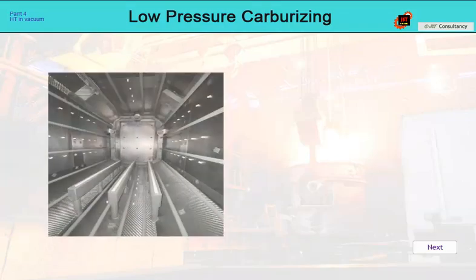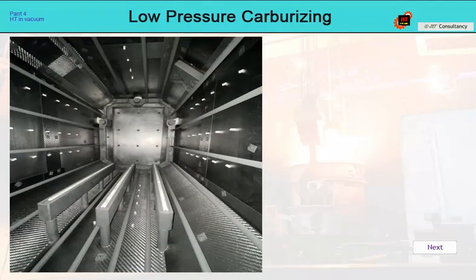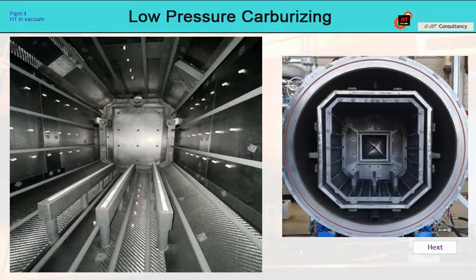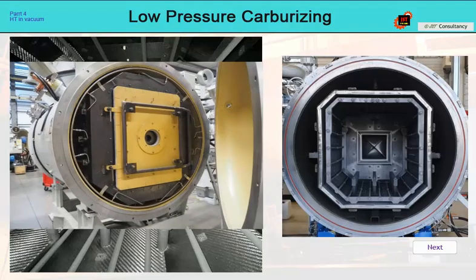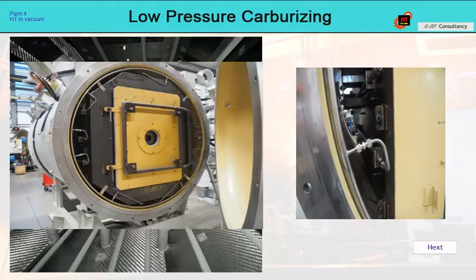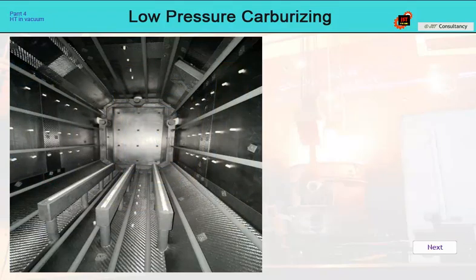The basis of this process is a vacuum furnace, essentially the same design as conventional vacuum furnaces. The only difference is that between the cold wall of the vessel and the heating chamber, there is a system of tubes designed to distribute the saturating gas evenly in the space of the heating chamber. The gas itself is then fed into the working chamber through a system of nozzles. These can be ceramic or made of quartz glass.